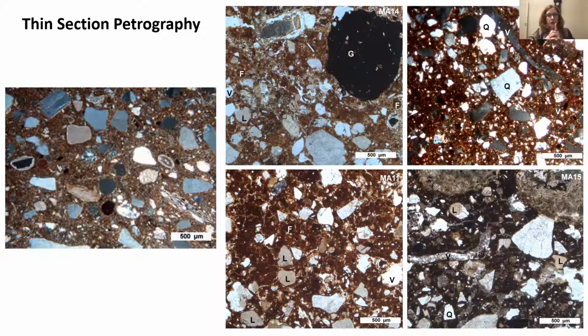We put on the left of the slide the only outlier that we have within this fabric. This is MA5, sample number 5, and this is the exception to the main fabric, since it presents a calcarenite fabric with a brownish color and the presence of micritic calcite grains. This is actually an outlier within all the other samples that we have in the Palace of Malia, but it's not an outlier in the whole settlement. Mudbricks of a similar fabric are actually found both in Delta and Quartier.